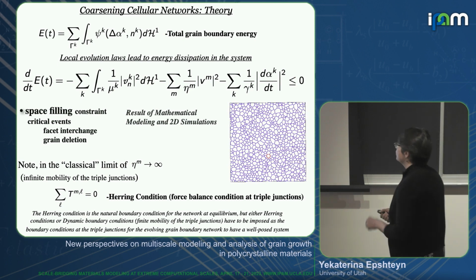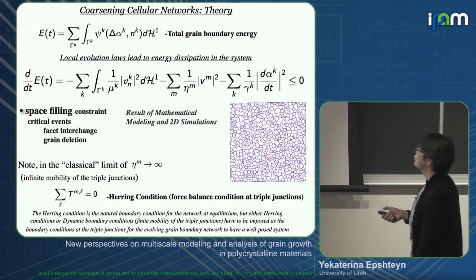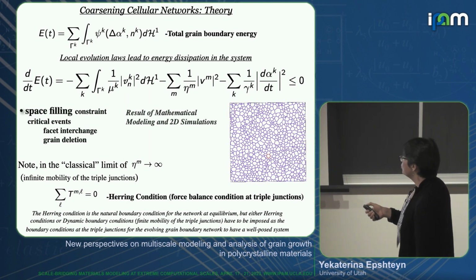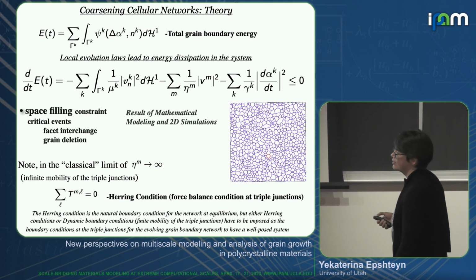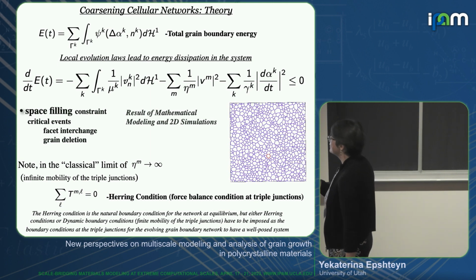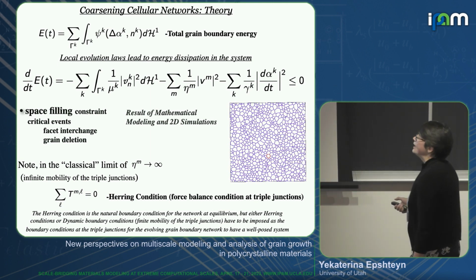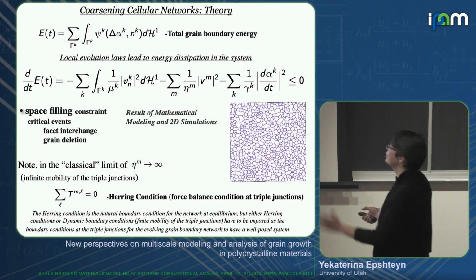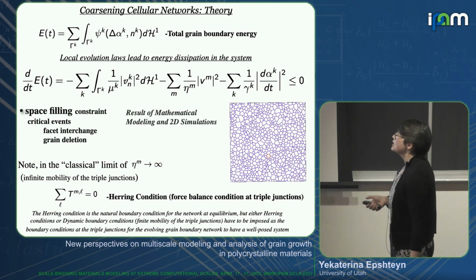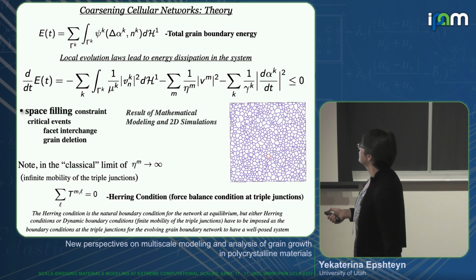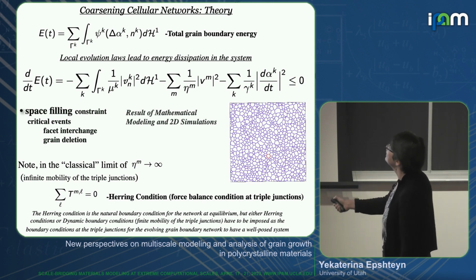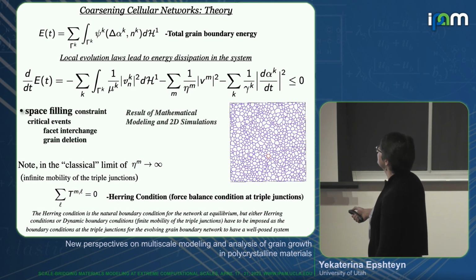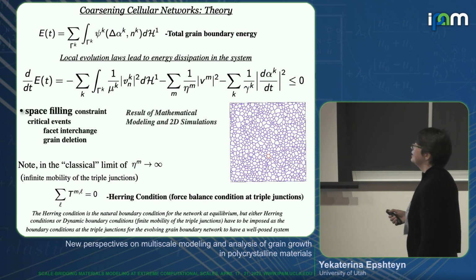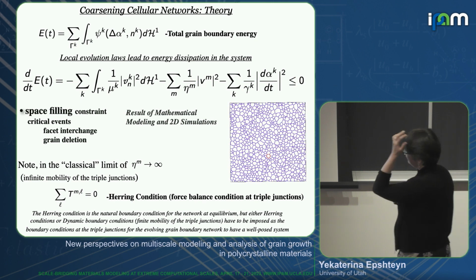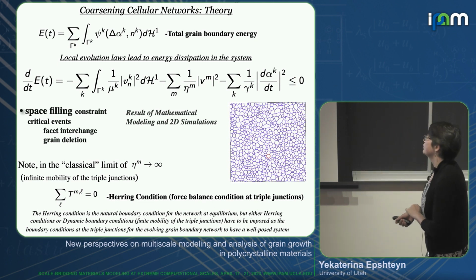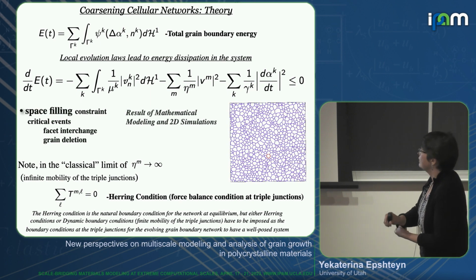And due to the way we imposed local evolution laws, we can show that the total energy decays with time. So the system is dissipative, and we have 3 different relaxation time scales, different dynamics that contribute to that dissipation. So we have dynamics of grain boundaries, dynamics of triple junctions, and dynamics of orientation. So the way I wrote here is through dynamics of orientations, which can be rewritten in terms of dynamics of misorientations as well.